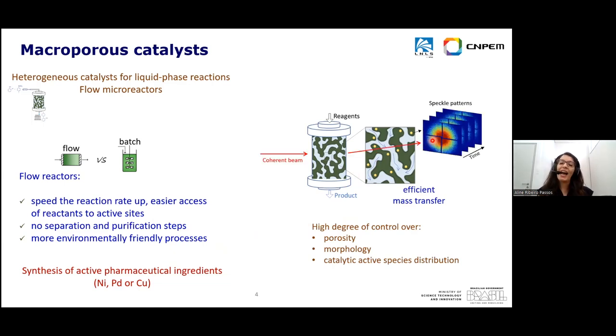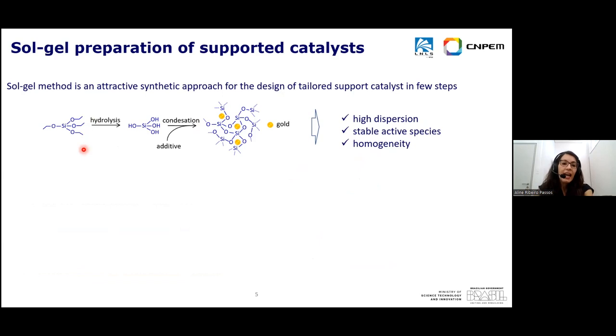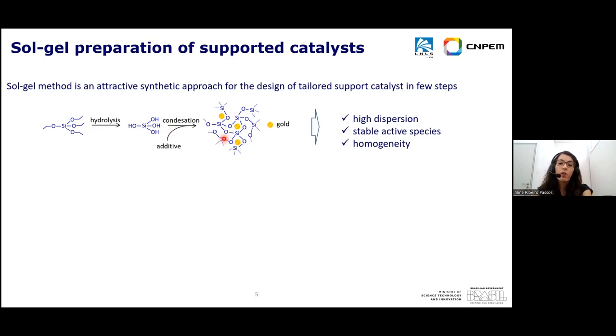In this presentation I show how XPCS can help you understand the formation of porosity and the distribution of the active phase. There are several approaches to produce this kind of material. A very attractive synthetic approach is the use of sol-gel synthesis. Using this method, we can prepare a catalyst in very few steps, without needing high temperature or high pressure; the solvents are usually water or ethanol. In this method, we start from an alkoxide or a metal salt, which then undergoes hydrolysis and polycondensation reactions to form the gel network.